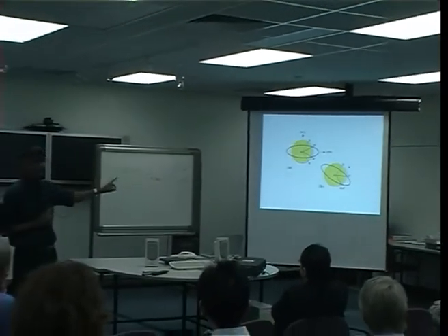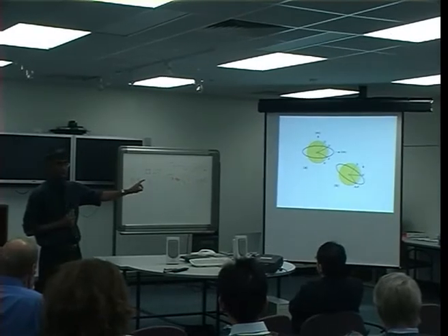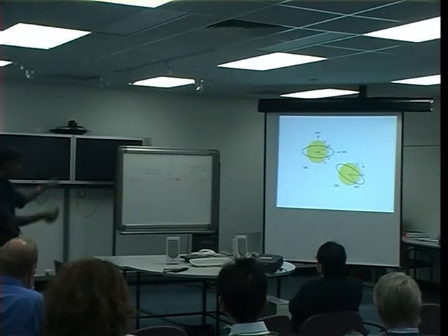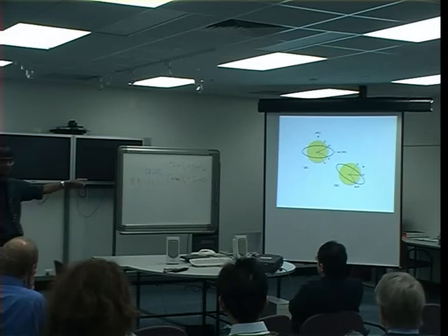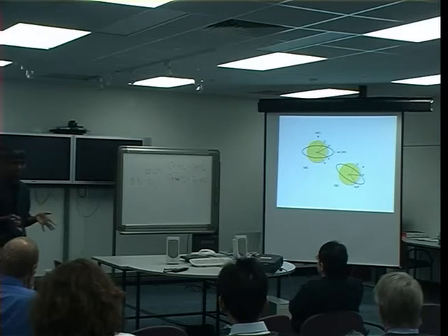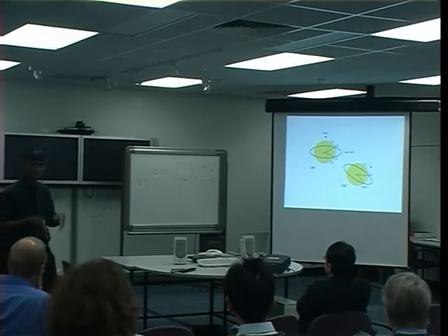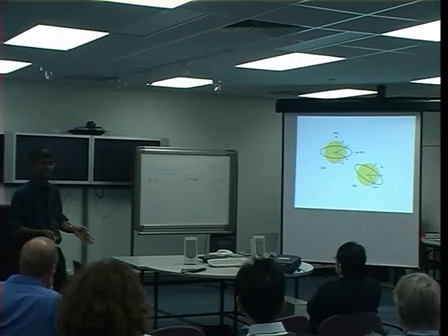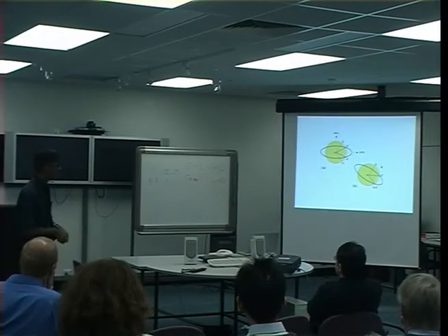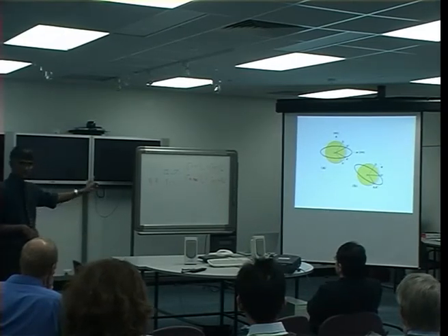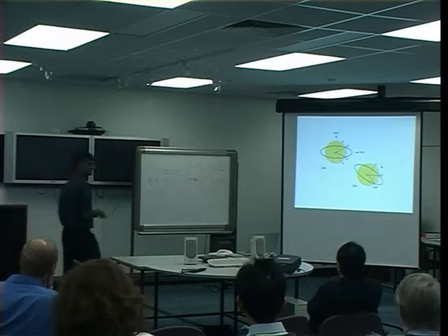Of course, there is no way I can produce two invariant lines. Whatever rotation I choose, you won't get both those lines to come into coincidence. So it's still inconsistent with the observed shape deformation, which is an invariant plane strain. But we've explained completely the orientation relationship. For any martensitic transformation using this simple method, you can exactly predict the orientation relationship. Is everybody happy with that?